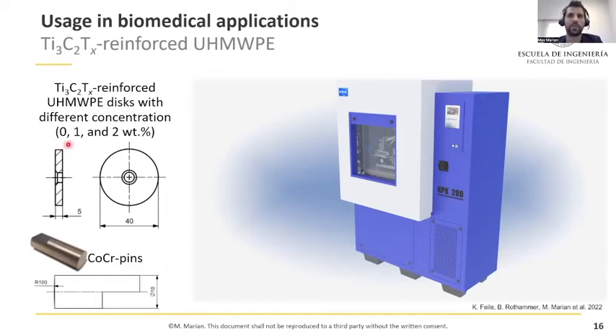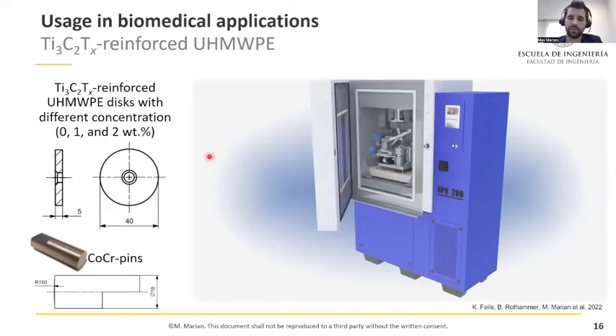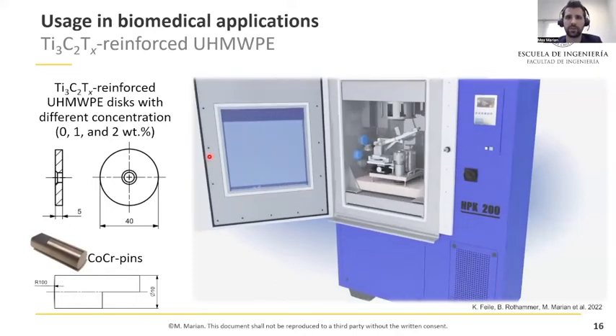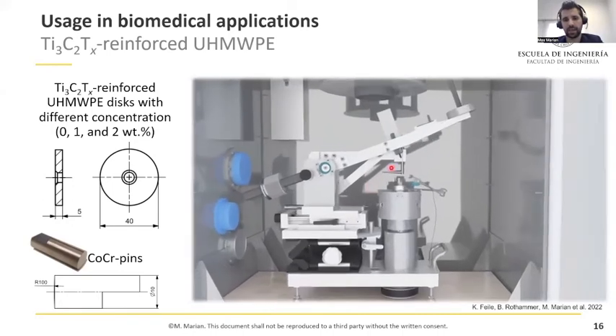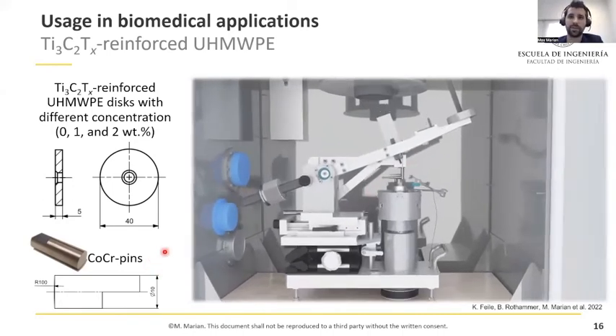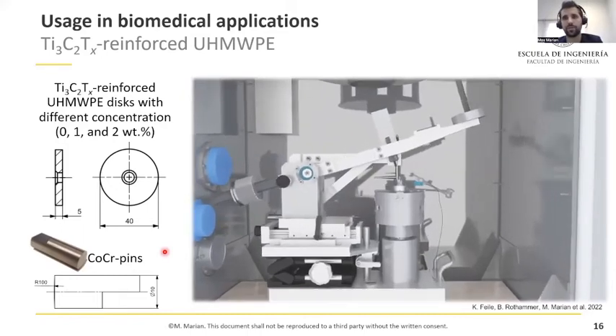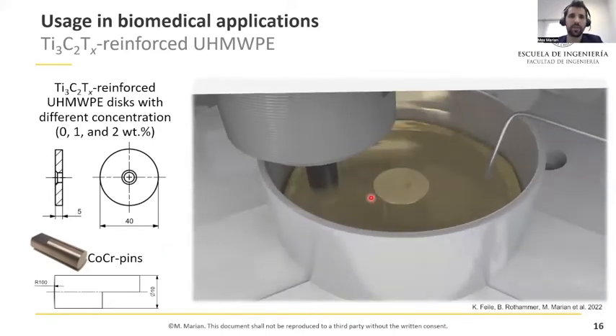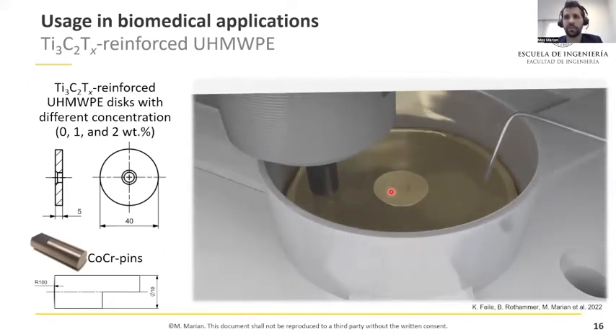And thereby we varied the concentration of MXenes. We had a reference case without MXenes, and 1 and 2 weight percent MXenes. And besides structural and mechanical properties, we also investigated the biotribological behavior using a pin-on-disc tribometer, as we can see in the animation on the right. So basically, as a counterbody, we used cobalt chromium alloy pins because they're the gold standard for femoral components of knee replacements. The contact we can see here was lubricated with bovine calf serum as a substitute synovial fluid, and the test chamber was tempered to 37 degrees Celsius, representing human body temperature. And the contact conditions were chosen in such a way that they were representative of wear critical conditions of knee replacements.